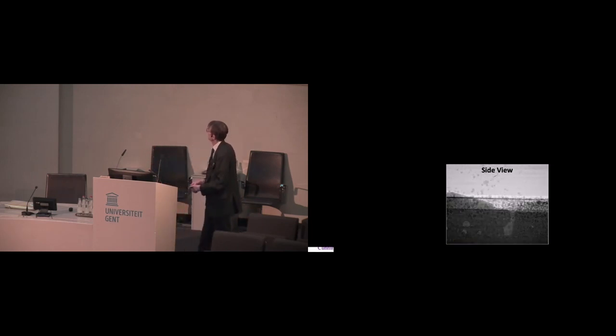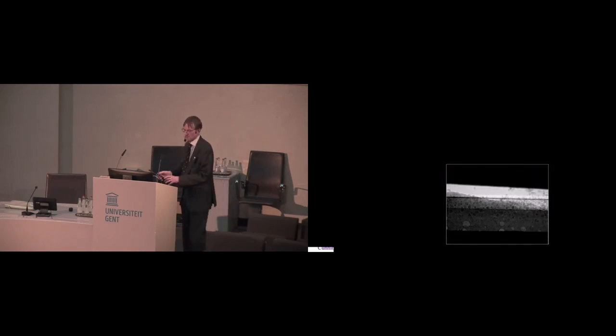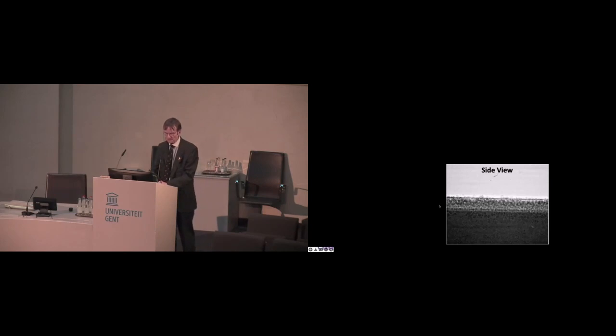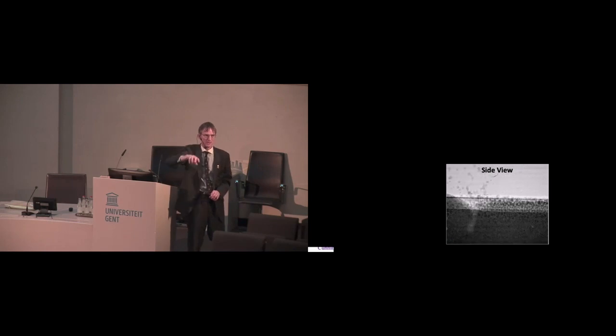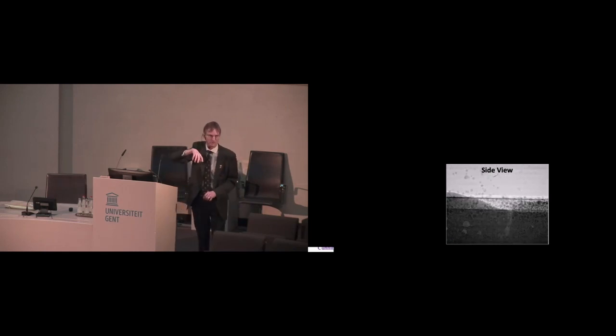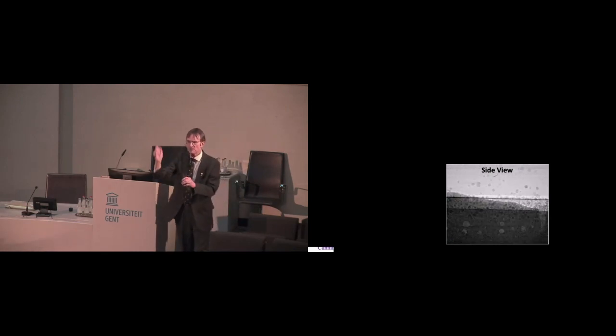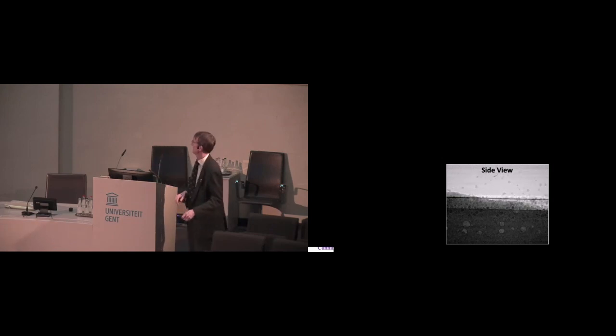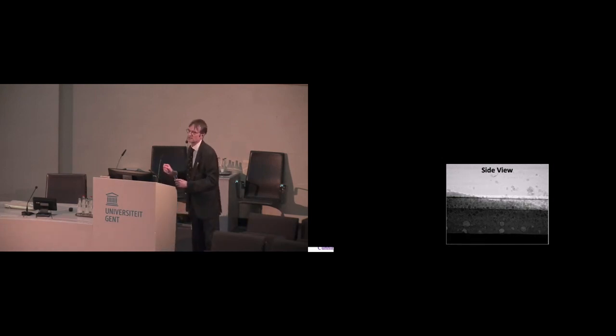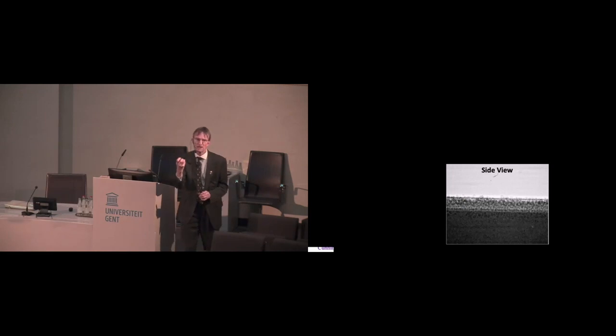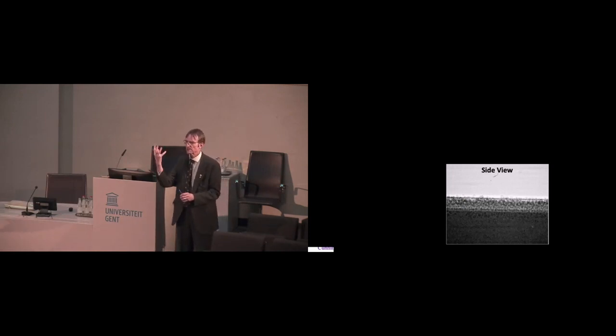It'll come back. So what you see, and I'll have to play this a few times, is you see that quite sharp depression. And so that is, in fact, the laser drilling its way into the metal. You can see powder particles on top, and you can see as the vapor comes out, it's blowing powder all over the place. And furthermore, you can see that that keyhole is leaving behind bubbles. The bottom of the keyhole is unstable, it pinches off, and it's depositing these bubbles.